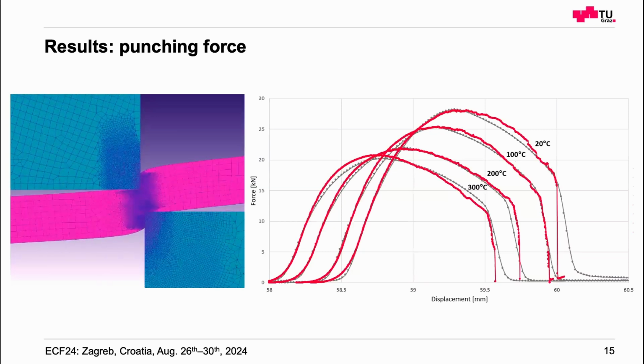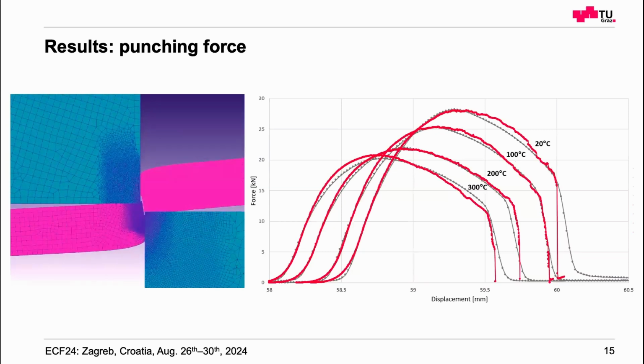To compare with the real punching, we did the simulation of the real punching. And you see here also the force over displacement curve from our real test, which is the red color, and the simulation is the gray curve. And you see our model matches the real testing very well.